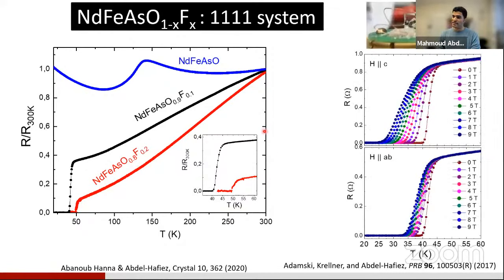And since we have a single crystal, you can measure both orientations, because in a single crystal you have the AB plane and the C plane and so on. That's important for applications and for anisotropy effects. So for H parallel to C, that's the C plane, and also you rotate the sample 90 degrees and measure the same, you get different results between here and here. That confirms the high quality of your materials.